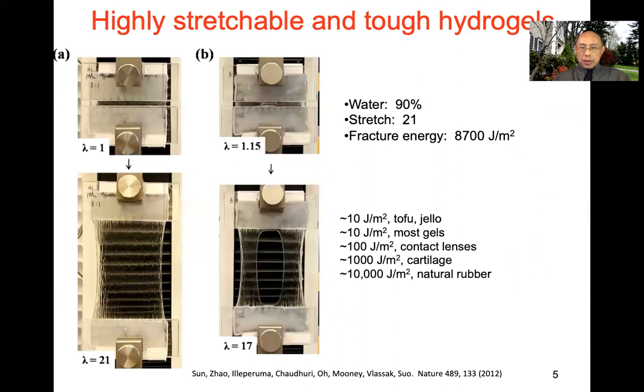In recent years, myself and several other groups have been trying to create tough hydrogels. Here's one version we published in 2012. The hydrogel is really very tough. So here is a hydrogel. Hydrogel is transparent. What you are looking at is a black background. We can stretch this hydrogel to 21 times. You can see 21 times.